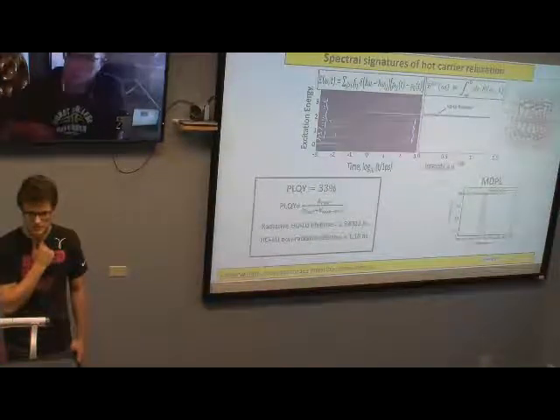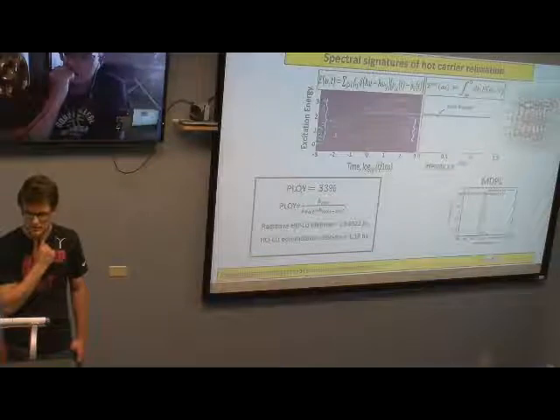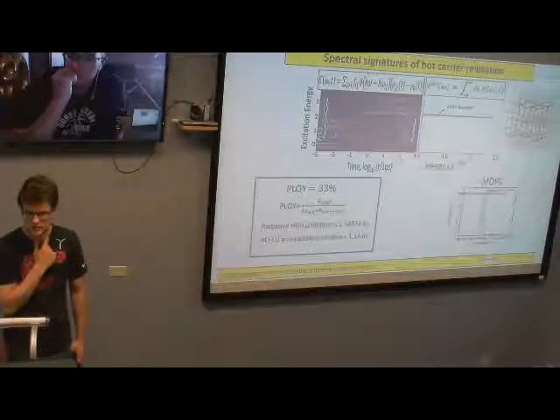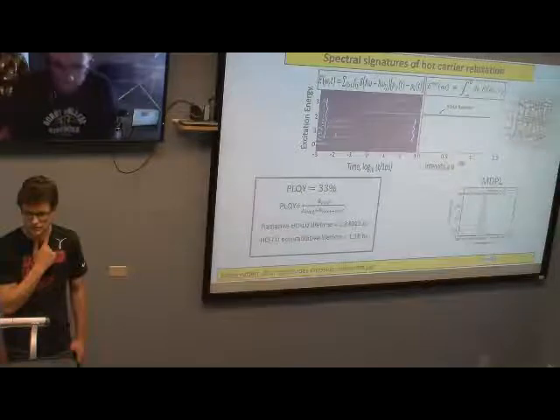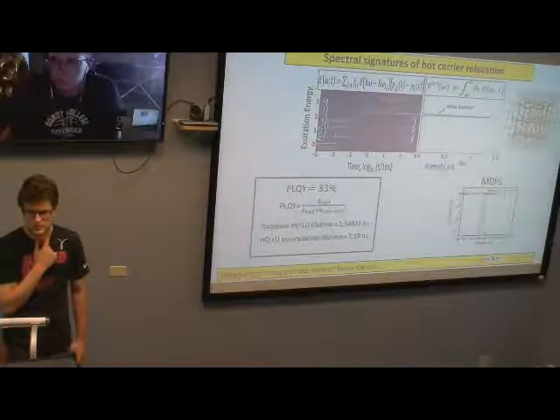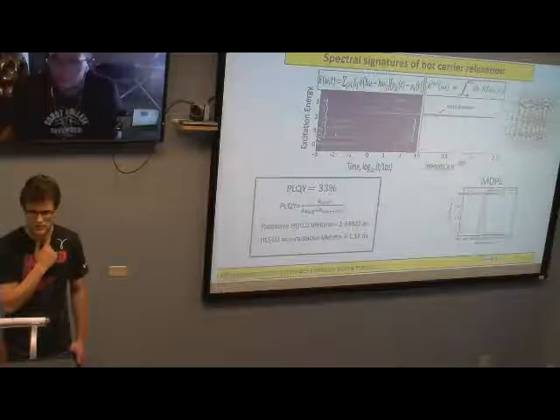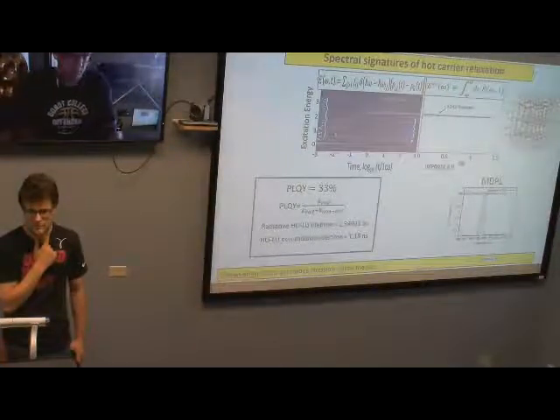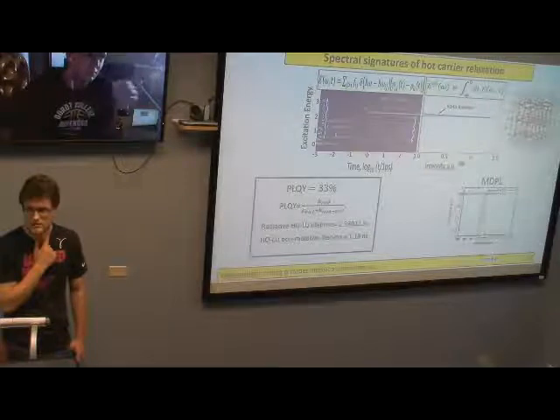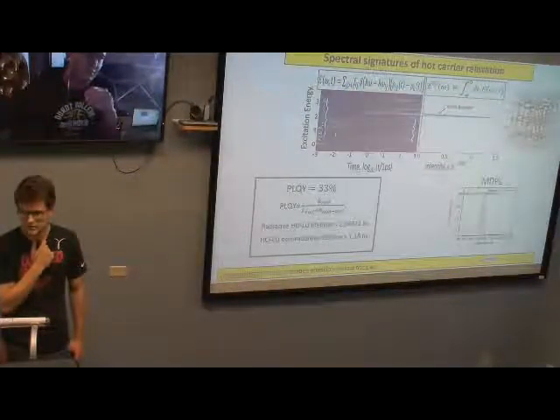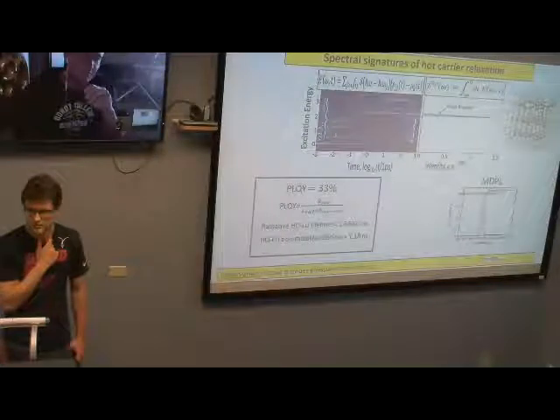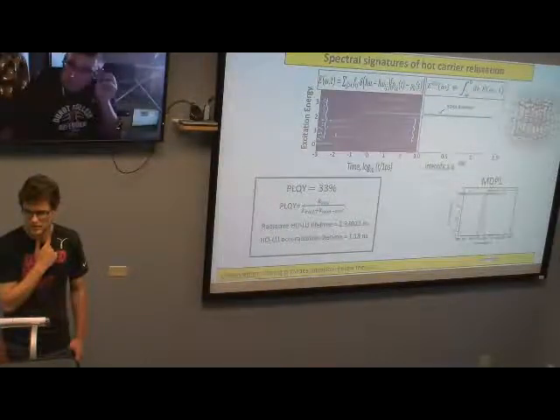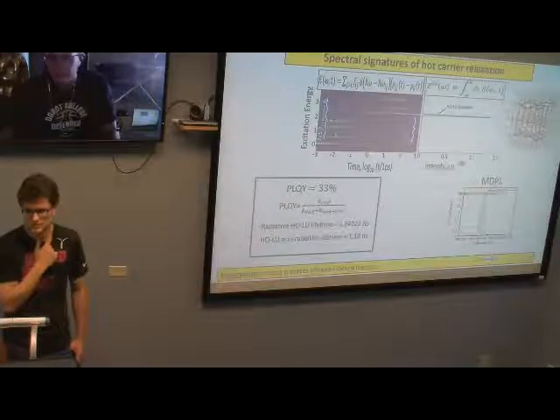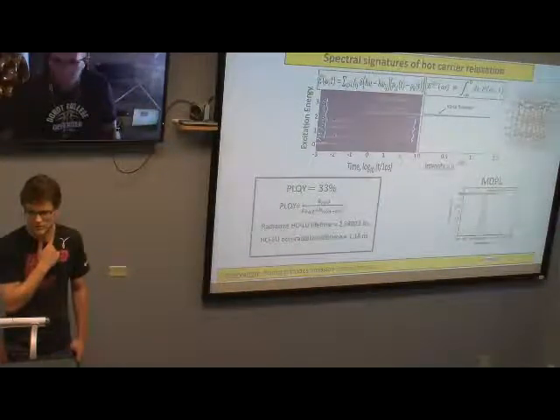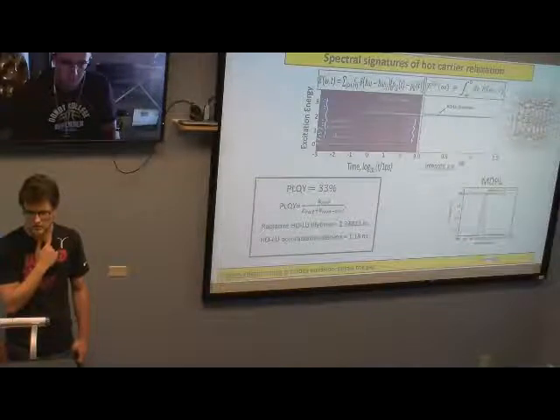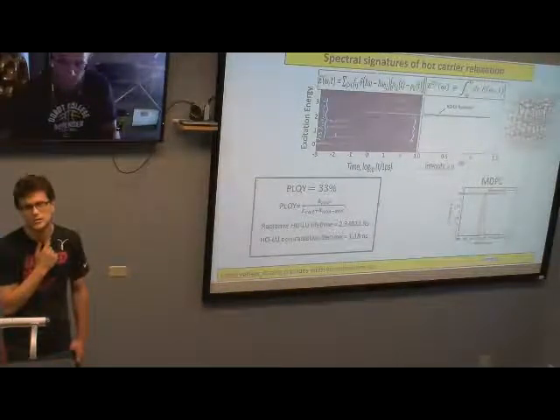But our temperature is actually defined in best cases probably plus minus 20 or even 30 Kelvins, right? So it means you're really not having a temperature of 300, you're having, well, a temperature in absolute numbers somewhere around 350. It's not very helpful to compare absolute numbers. If one would check trends, how the line widths would change as a function of temperature, then it may show right trends, as John was doing in 2016, right?